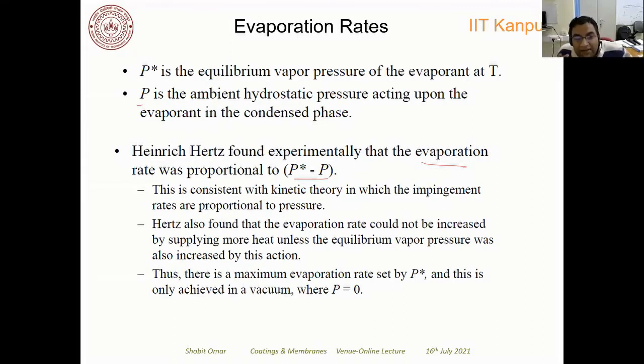And an important thing is that Hertz also found that the evaporation rate could not be increased by supplying more heat. It cannot be increased unless you are changing the temperature and thereby changing the P star value. As I said, from the Clausius-Clapeyron relationship, P star is only dependent on temperature. Even if you are giving a high amount of heat and it's not changing the temperature, then evaporation will not change. Thus, there is a maximum evaporation rate set by P star, and this is only achieved in a vacuum. So P star minus P is a very important term.